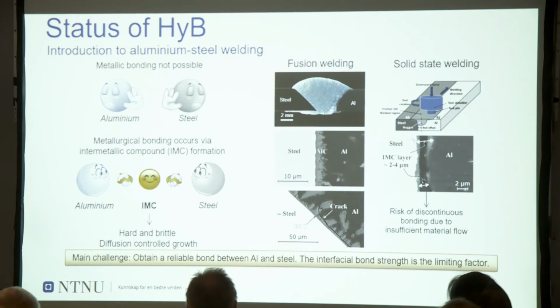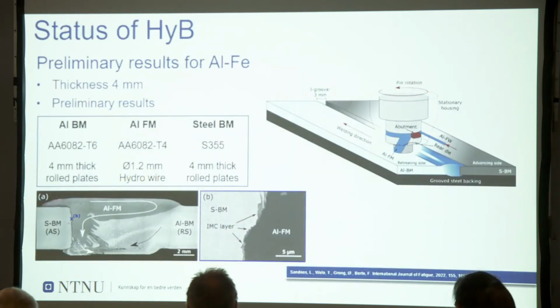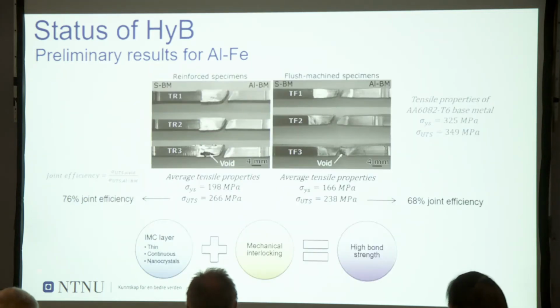Now we go to the most complex part, which is the HyB of aluminum steel. You know that aluminum and steel do not like to be boyfriend or girlfriend together. So it's quite difficult to obtain a very good bonding between these two materials. And so what we have tried to do was to use HyB for this purpose, and to control the intermetallic compound that was obtained during the HyB process. The preliminary results for aluminum steel weldments refer to a thickness of 4 millimeters.